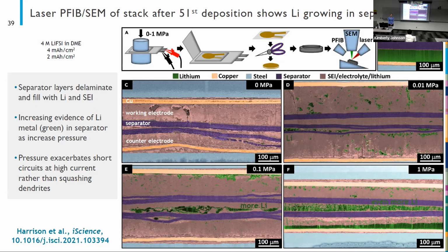Yeah. You mentioned with Dr. Croker about the damage that happens to the LiFSI during the dipping. Have you ever done any sort of characterization that has to test the effect of local heating on the electrolyte? We have not. So these are all done at cryo temperature. So the electrolyte is completely frozen, essentially during the characterization experiments, all of the imaging experiments.